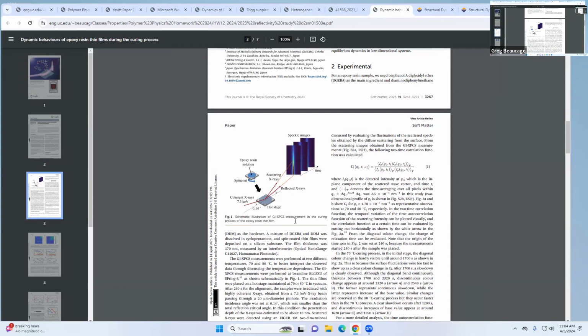Yeah. So I'm not as good at reflectivity, but you can either do transmission experiments where you shoot straight through a bulk material and probe that scattering volume from one end to the other. You can also do experiments where you're reflecting off of a surface, and there you're actually probing different layers of that different geometry. What if I'm talking about a casting or a coating process where I want to make a nice thin film? Looking at a bulk chunk is not going to be that useful. Here, you can lay that out, get a film like an epoxy coating, and then use reflection X-rays to look at the dynamics as well.